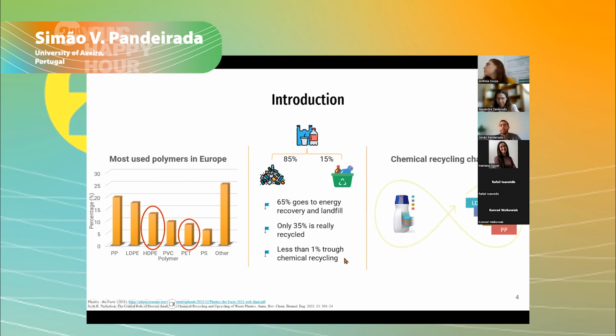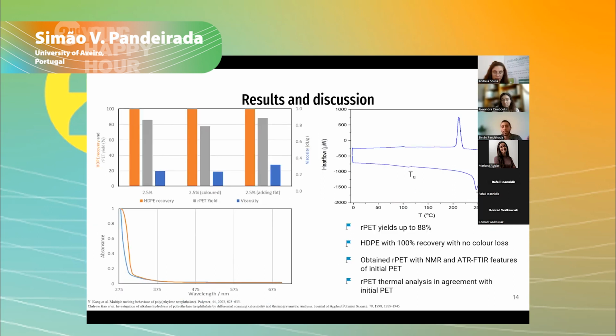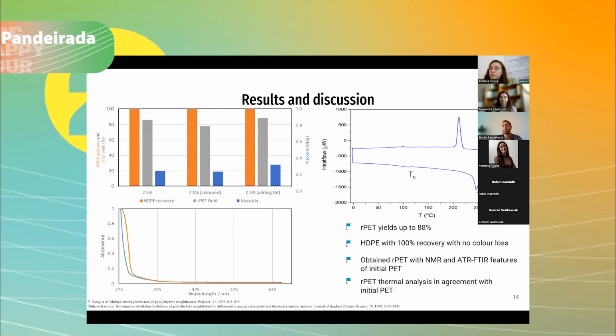One of the major challenges now in the recycling industries is the recycling of multi-layer packages containing different kinds of plastics, and chemical recycling is in the first line to solve this problem. In this regard, we obtained with this procedure up to 88% yields of recycled PET, with 100% of recovered polyethylene, and our recycled PET presented really similar features, not only thermally but also in terms of spectroscopy, in comparison with the initial sample and the values already reported in the literature.